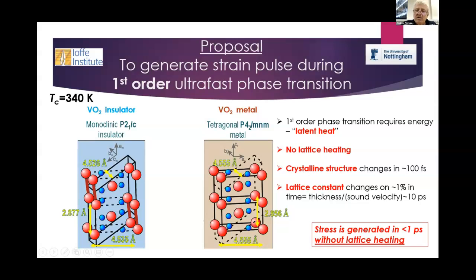The important thing is that there is no lattice heating during this phase transition, because it is a first order phase transition. The crystalline structure changes in about 100 femtoseconds, studied with X-ray and electron diffraction - this is all known. The lattice constant changes by about 1%, but it doesn't change that fast - it cannot actually change so fast because it is related to the size and geometry of the system, and to the sound velocity in the material.